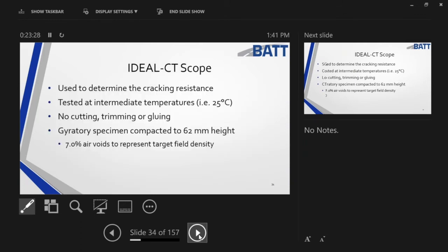So the ideal scope here is, again, I want to just understand the basic cracking resistance of a test. Now, if I really want to make it more generic, what I'm really trying to do is look for the peak strength, but then after my pavement forms that initial crack, how does it propagate, or how does that crack move on? And that's where mixture cohesion and adhesion really begin to work together. And how am I holding that mixture together to keep that crack from growing? So mixture cohesion and adhesion is something we don't talk a lot about, and we sure didn't measure until lately. The ideal CT test, I like it because, again, no cutting, no trimming, no gluing. And again, I'm just targeting a typical air void density that I would try to match in the field.